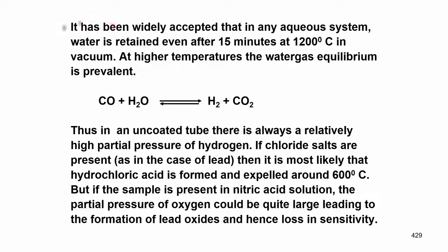And what we want to say further is a few small points. For example, it is widely accepted that in any aqueous system water is retained even after 15 minutes at 1200 degrees centigrade in vacuum. Some little tidbits I am giving you. So, do not be fooled that water can be removed completely in any given system easily.